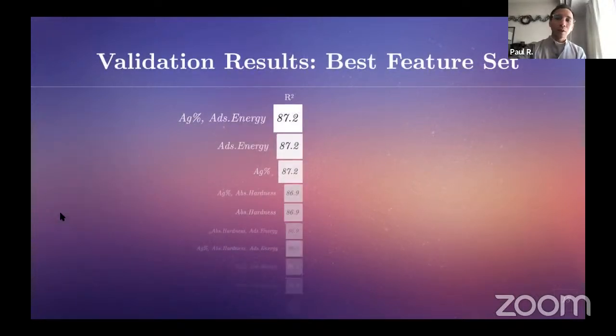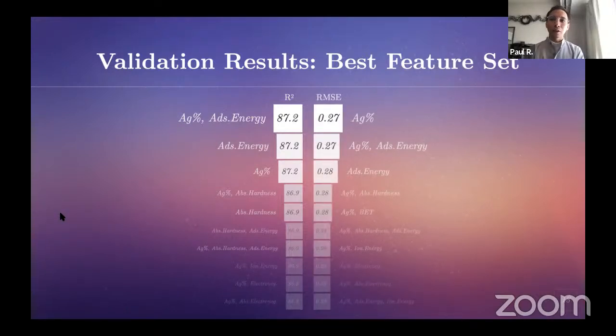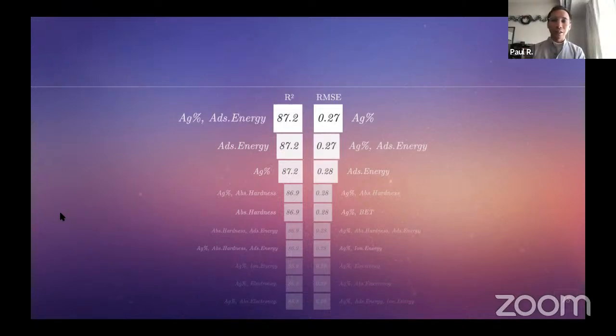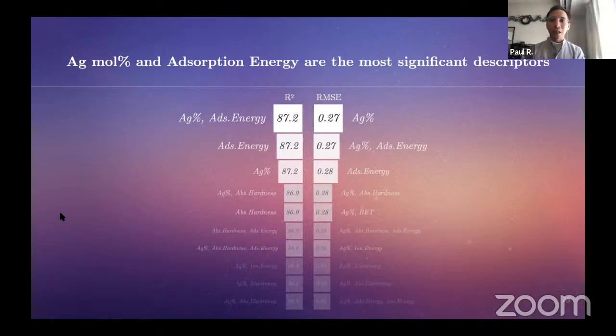Let's now talk about the results. During feature selection, we evaluated the models trained on different combinations of features, and we found that Ag concentration percentage and adsorption energy features produce the highest scoring models for both R squared and RMSE. Looking at the top 10 feature subsets for both of these metrics, we can see that most of them include either Ag% or adsorption energy. Thus, given these results, we trained the model on Ag% and adsorption energy and then tested different kernels.